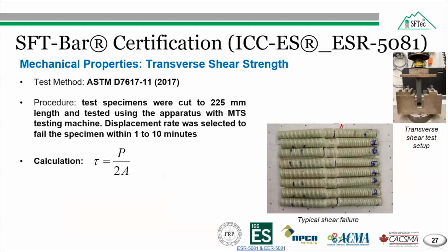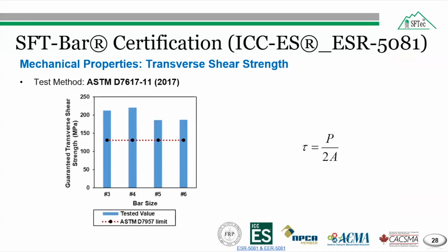And we placed the upper plate onto the bar and centered the apparatus in the MTS universal testing machine. So the displacement rate was selected so that the product should fail within 1 to 10 minutes, and force was applied uniformly without subjecting the specimen to impact. So after testing the samples in shear up to failure, the transverse shear strength was calculated using this equation, where P is the failure load in Newton and A is the FRP bar area in square millimeter. For the SFTech GFRP bar, the average transverse shear strength was greater than the 131 megapascal requirement in the ASTM D7957.